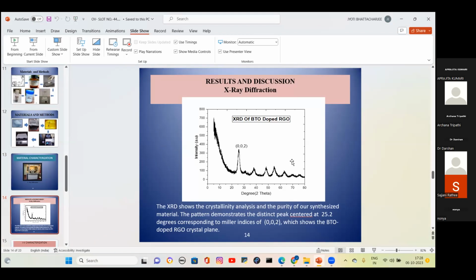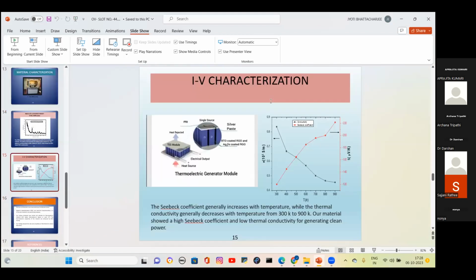I've also done IV characterization, and the Seebeck coefficient from this IV characterization shows that it generally increases with temperature from 300 to 900 Kelvin. And the thermal conductivity decreases with increasing temperature. So our material has shown a high Seebeck coefficient at 900 Kelvin. It has shown 220 microvolt per Kelvin, with low thermal conductivity for generating clean power.